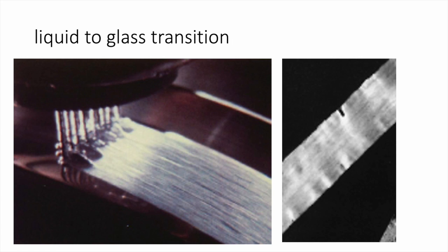The way we make metallic glass is to take liquid molten metal and pour it onto a rotating water-cooled copper wheel, giving a cooling rate of the order of a million degrees centigrade per second. Given that large cooling rate, the atoms cannot have sufficient time to crystallize and therefore the metal actually forms as a glass — a solid, but with atoms arranged in a random array rather than a periodic array.